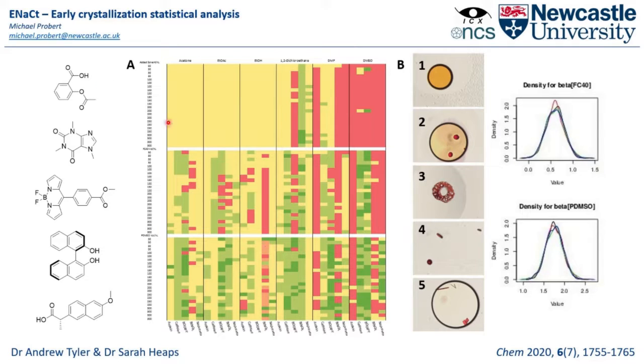So even with no oil encapsulation, some systems crystallized reasonably well, suitable for analysis. But as we progress through to our encapsulated systems where we've slowed down the evaporative loss, we definitely have an increase in crystallization success. And interestingly, at this point, there is a different success rate for combinations of oils with different solvents. So the combination of oil and solvent is very important. So the oil is not quite as innocent in this as we might think.